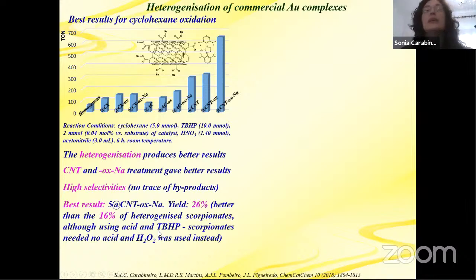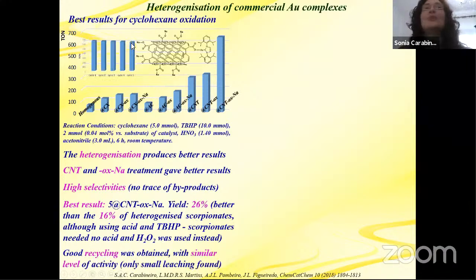I showed before. But here we had to use acid and tert-butyl hydroperoxide, while the scorpionates did not need acid, and H2O2 was used instead. So we obtain better yield, but we have harsher conditions. So we have to choose what we prefer. And see here a good recycling was obtained and a similar level of activity, only small leaching was found.